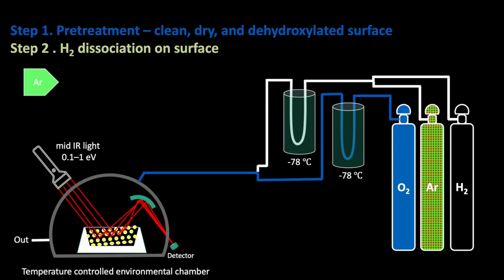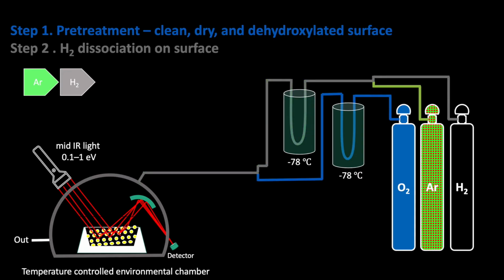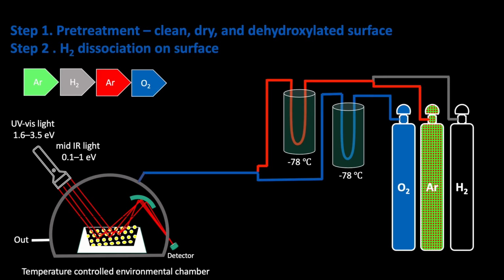At the beginning of step 2, we collect a single beam spectrum as reference under dry argon environment at 300 Celsius. Right after argon flush, we flow hydrogen over the titanium surface to produce electrons and monitor it continually with IR or UV visible light. After collecting spectra under hydrogen, an argon flush step is used to prevent the mixing of the remaining hydrogen gas with oxygen. The last sequence of this step 2 is reoxidizing the surface.